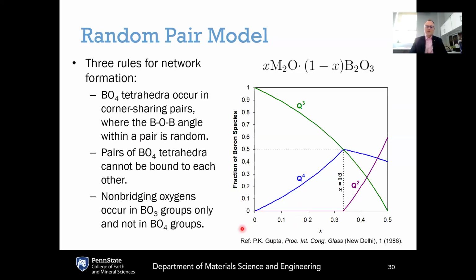Now, Prabhat Gupta developed a model that describes what is the fraction of boron in different coordination states. It's called the random pair model, and it's based on the notion that the tetrahedral boron units, the BO4 units, occur in pairs, and that the pairs of BO4 tetrahedra cannot be bound to each other, and that non-bridging oxygens occur only in the trigonal groups, the BO3 groups, and not in the tetrahedral BO4 groups.